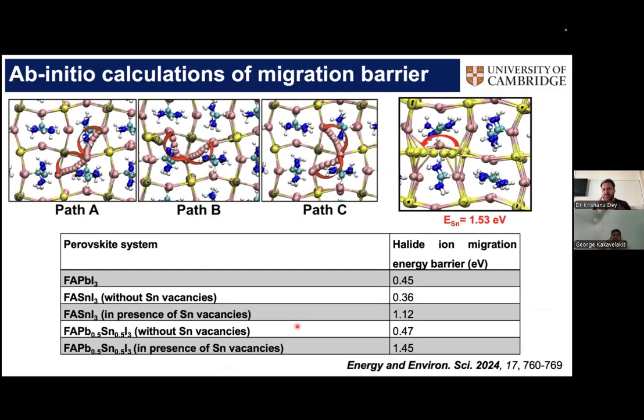And then to understand what is happening atomically, our collaborators did some ab initio DFT calculations. What we find is that if you go from a pure lead system to a pure tin system, let's say from lead iodide to tin iodide, we don't see a huge change in the ion migration barrier. So these are pretty similar.